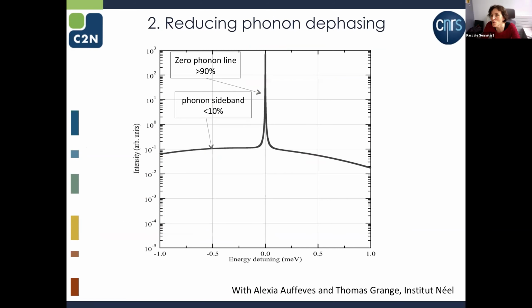Then we worked on reducing the coupling to phonons. Phonons manifest themselves in the emission of a single emitter with what we call the phonon sideband. When you have a two-level system, it should emit a photon at a very precise frequency. This is what we call the zero phonon line. This is the intrinsic emission. But if your emitter is coupled to the vibration of the crystal, it can also emit a photon while emitting or absorbing a phonon, so exchanging vibration energy with the crystal. And this is what we call the phonon sideband.